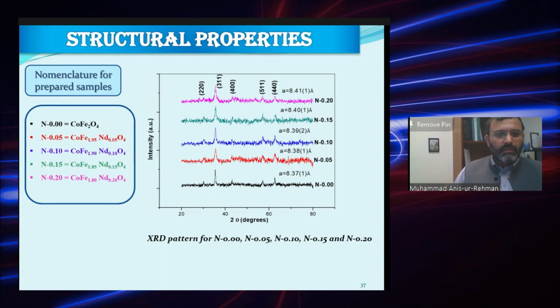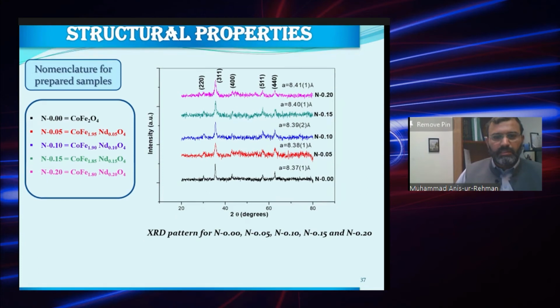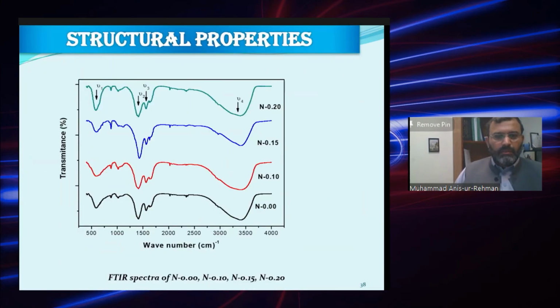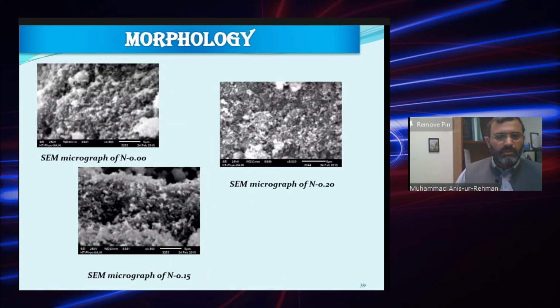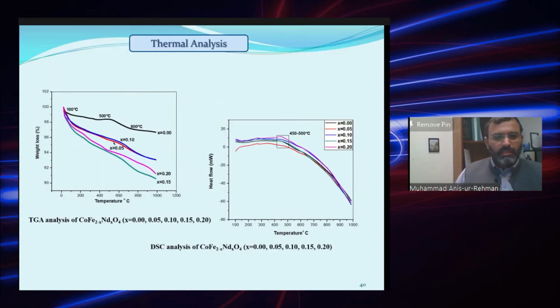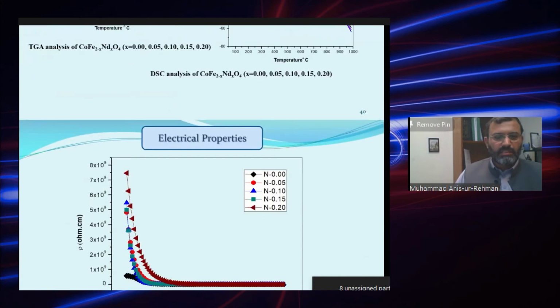In the second section, we varied the ratio of the neodymium at the iron site to see how that is affecting the properties of the cobalt ferrite. XRD also confirmed the single phase spinel structure in the cobalt ferrites. Particle type morphology could be seen in the SEM, and in the DSC and TGA analysis, almost in all the cases, the transition was in the region of 450 to 500 degrees centigrade. So these materials were sintered at 550 degrees centigrade for further characterization.